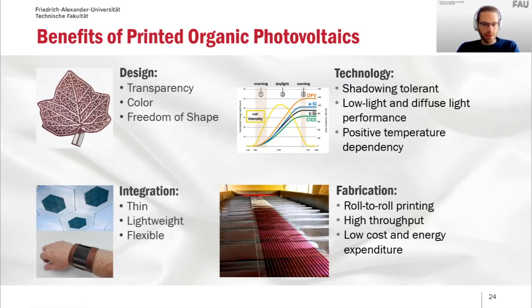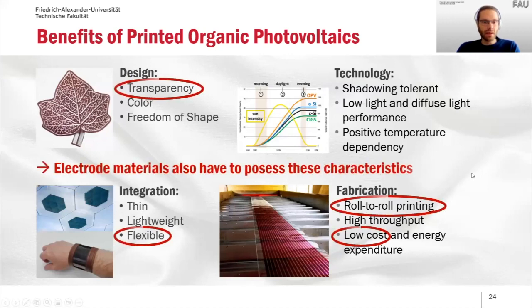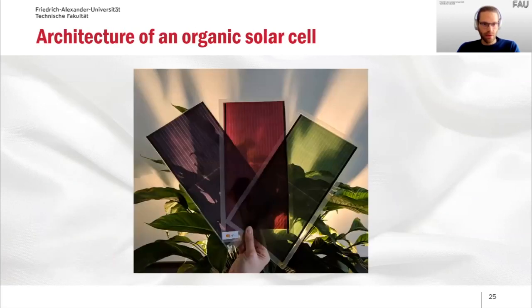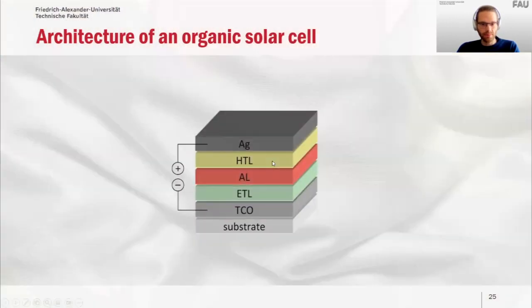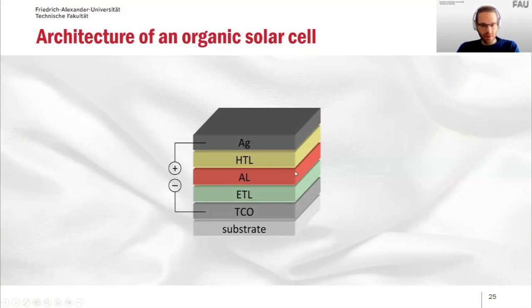So the organic materials, which are the active layer in this solar cell stack, provide all these characteristics. But if we want to make a solar cell stack, also the electrode materials need to provide these characteristics. For example, they need to be transparent, otherwise we can't look through the module. So let's take a look at the architecture of such solar modules, take a look inside. The layers are printed onto a substrate, and the substrate is actually already 99% of the thickness of the whole module. Because the whole layer stack that is printed on top is actually less than 1 micrometer thick.